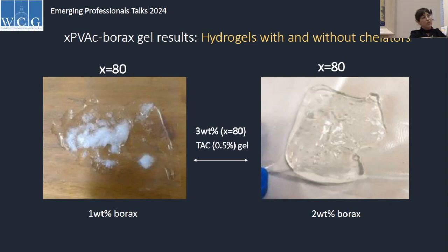But what my research did show is that an increase in the polymer and an increase in borax specifically actually results in a gel that goes from a gel that's not functional to a gel that is functional. So just that 1% increase in borax gives you a completely different result.